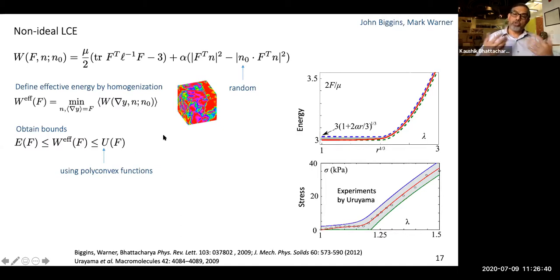And again, you use what are called polyconvex functions. You try to use known things and try to impose constraints in some relaxed way, and that gives you an upper bound. It turns out when you compute these lower and upper bounds, the upper bound is the dashed blue line, the lower bound is the red line, and you find that these are actually extremely, extremely tight.